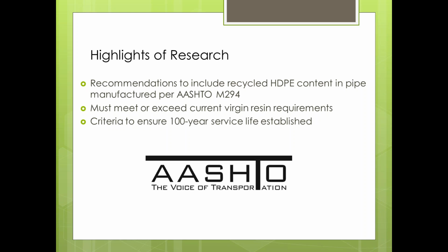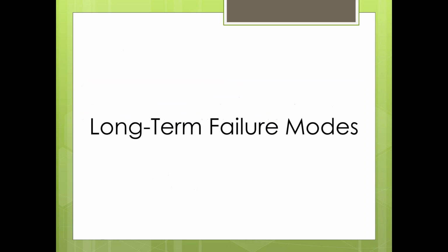The requirements for that product, when you use recycled, must meet or exceed the current virgin resin requirements. And there's also a standard recommended practice for ensuring 75 or 100 year service life based on a lot of the additional quality tests that are required for recycled resins above and beyond what's required for virgin. So it truly is a performance-based specification that is geared towards providing a product that is as good, if not better, than what's currently being used from a virgin resin standpoint.